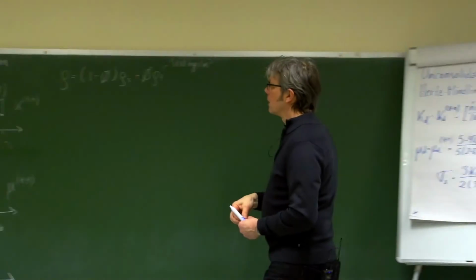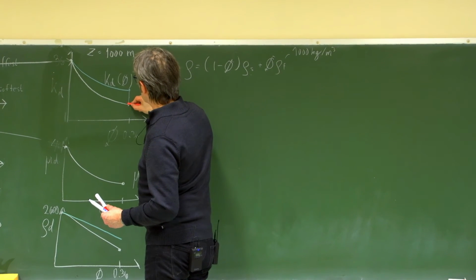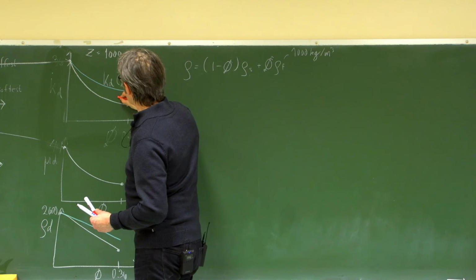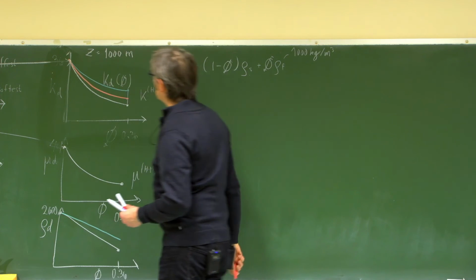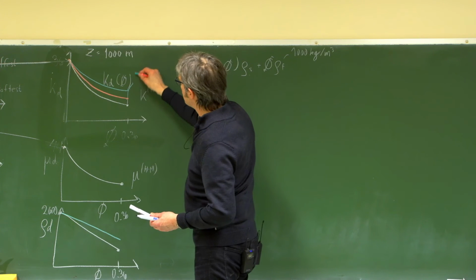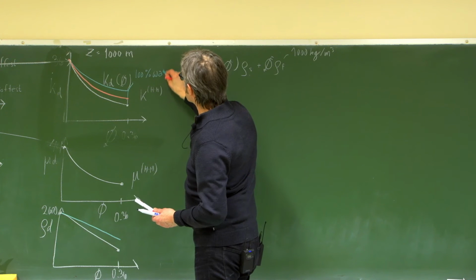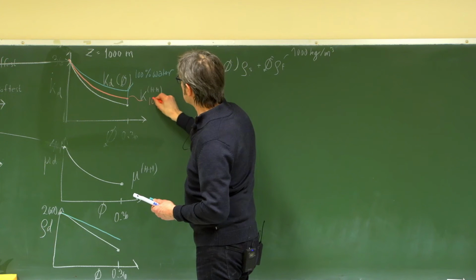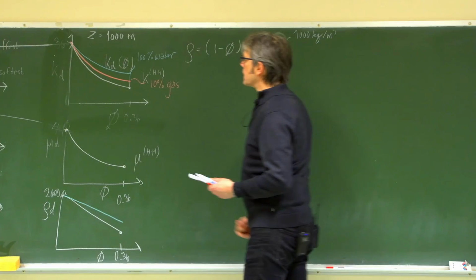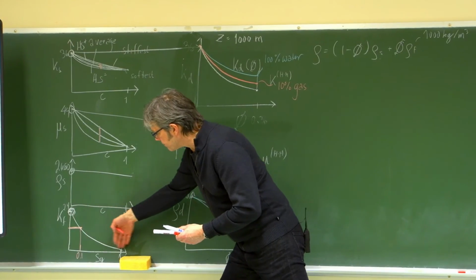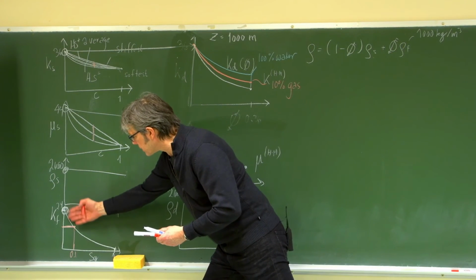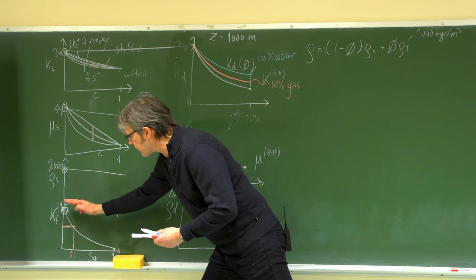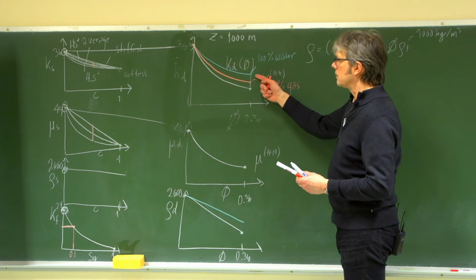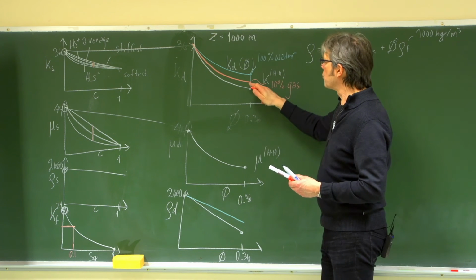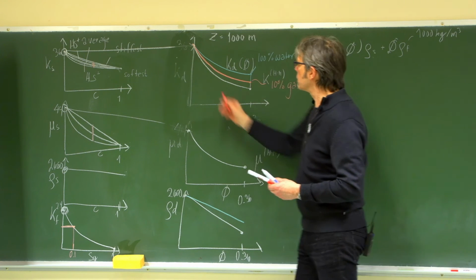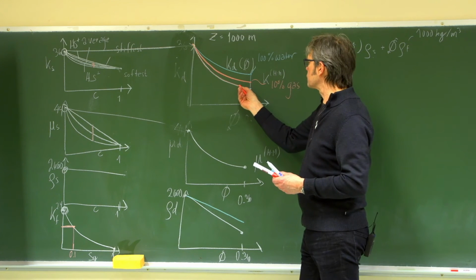And I do the same here. I would see that, okay, I had a huge drop here, it would move up here. And if I did it for every porosity value here, it would be up like that. So the blue one here is 100% water, while the red one is 10% gas. So you see that due to the harmonic shape of this one, huge effect of gas to begin with here makes the bulk modulus lower very fast. Makes a huge effect here. So just by adding a few percent gives a large effect, and then as you add more and more gas, you see the steps become smaller and smaller. So with 100% gas, I probably have a line that's just very close to the dry rock down here.